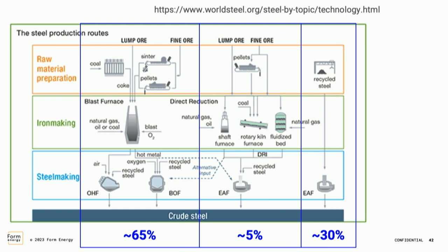Well, this is actually one of the detailed challenges of this. I'll speak to it since it's a good question. In the existing natural gas DRI route, you take iron oxide, which doesn't have any carbon in it. Since these processes happen with carbon-based reducing agents, they uptake some carbon. So industrially produced DRI today commonly has about 2 weight percent carbon inside of it. So you are charging the electric arc furnace with some carbon to be able to make steel. That's one of the challenges that has to get figured out for hydrogen-reduced DRI: how do you get carbon in? Because you don't just want to make pure iron metal. At the end of the day, you need steel, which has to include carbon. I don't have an answer for how to do that. That is a problem that has got to get solved.